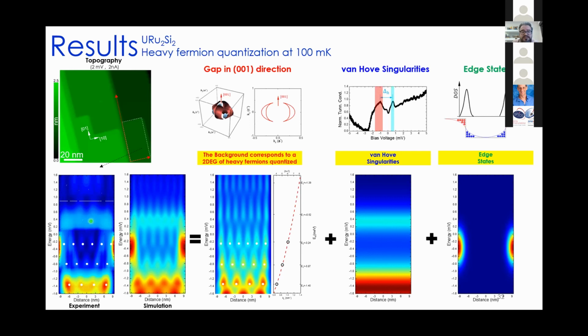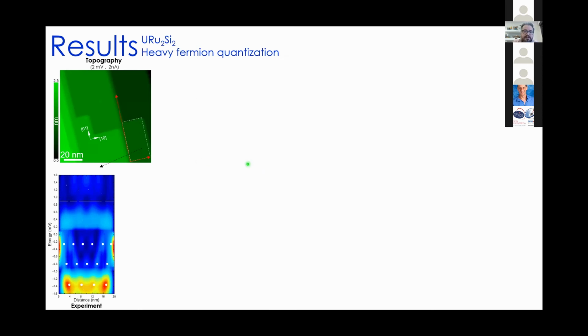Also, from this experimental data, we can extract another special feature to analyze the behavior of the quantized heavy electrons. We can extract more information. So we first measure the energy spacing, as you can see here, between consecutive levels, as we represent here with this arrow. We plot this spacing as a function of the energy, and here I put the average value of these values as a function of the width of the terrace. This is just the values that we get from this terrace. I'm going back to this plot in the next minutes.